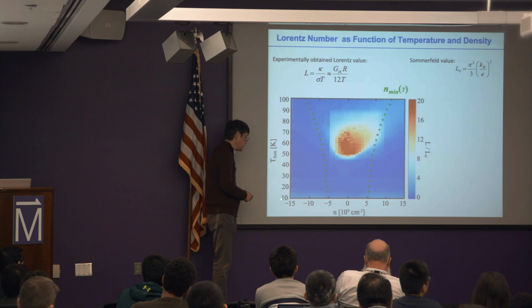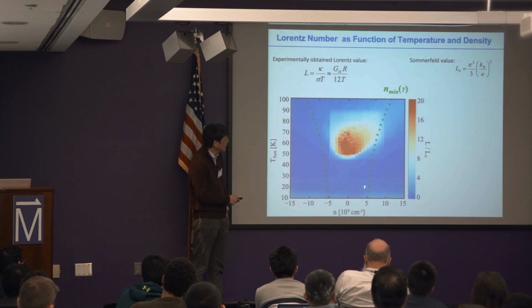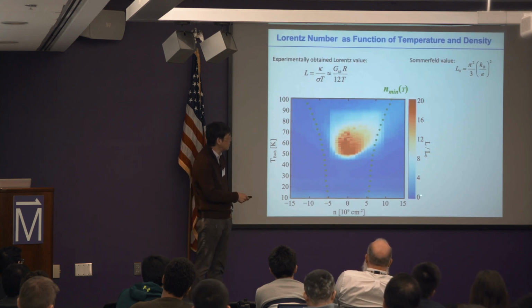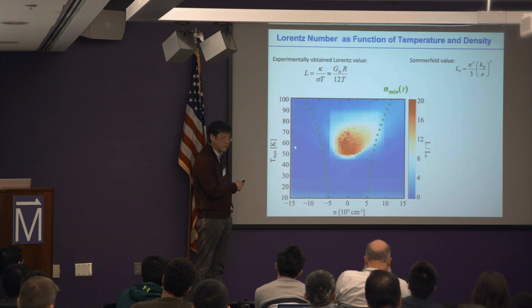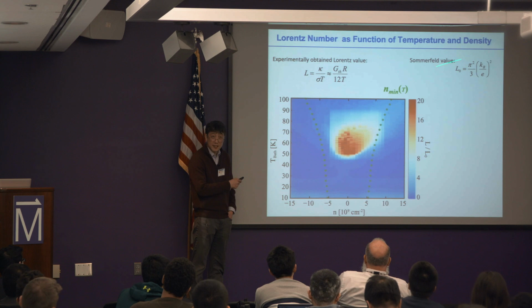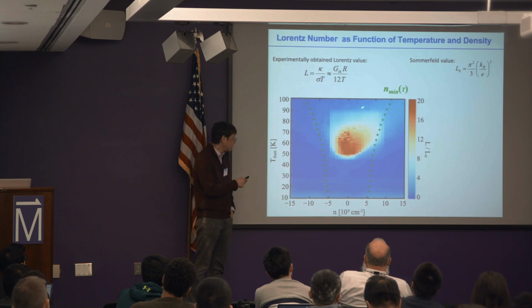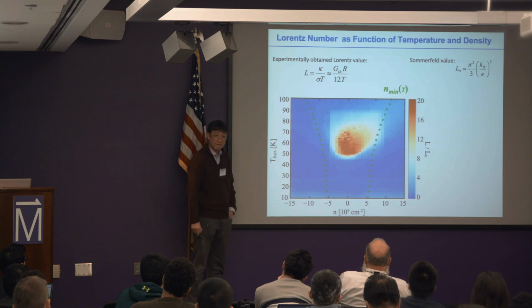So here's the temperature, here's the density, and the dark blue color is close to 1, close to the Lorentz number, right? So everywhere else the Wiedemann-Franz law works in the sample, except right at the Dirac point, around the Dirac point, and in certain temperature ranges. Right, that's what our data shows.